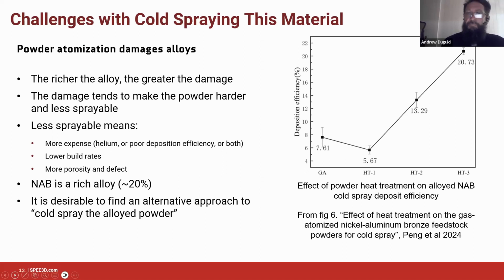Yeah, so here's kind of what I just said: it's difficult to spray highly alloyed powders. It's not impossible, but it does make life a bit harder. As a loose generalization, the higher the alloy content and the more aggressive the hardening mechanisms, the greater the difficulty. The powder's harder, it's more difficult to spray.